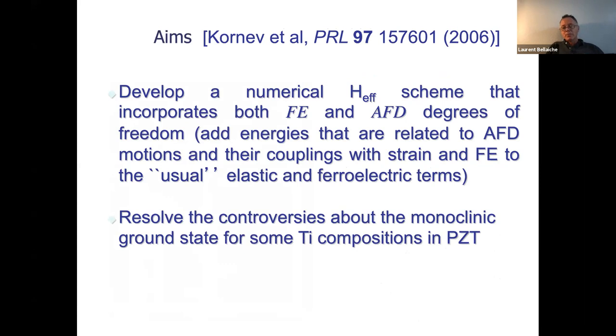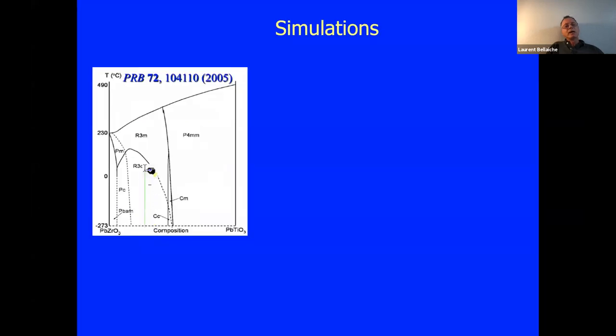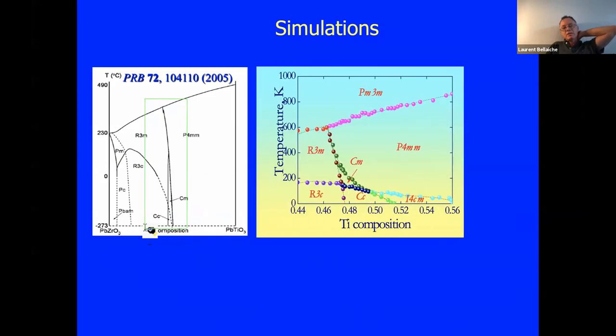What you do is quite simple. You basically add energy terms that are related to these AFD degrees of freedom, but do not forget to add the couplings with the strain and polarization. And we wanted to have an idea what's going on in PZT, and in particular, we look at these special compositional regions, about 50%, and this is what we found in these simulations.